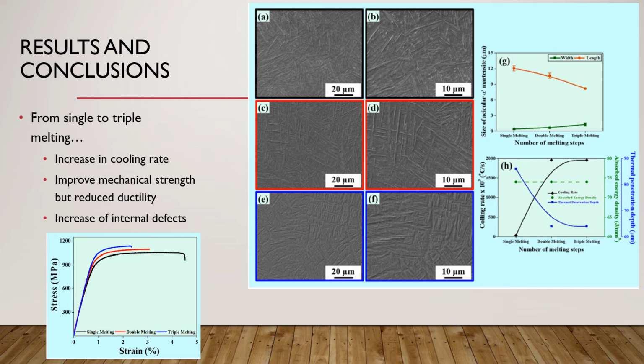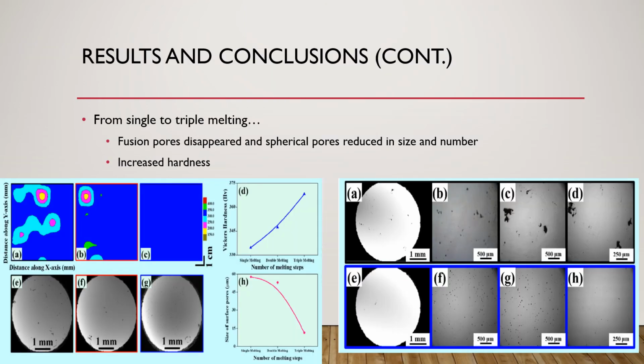At the same time, there was an increase in the number of internal defects, which gave small contributions to the mechanical strength. Also, we can see SEM images of single melting, A and B, double melting, C and D, and triple melting, E and F samples. In rapid solidification processes, as in the SLM process, when not enough time is given for the heat distribution, pores are formed due to the lack of fusion.